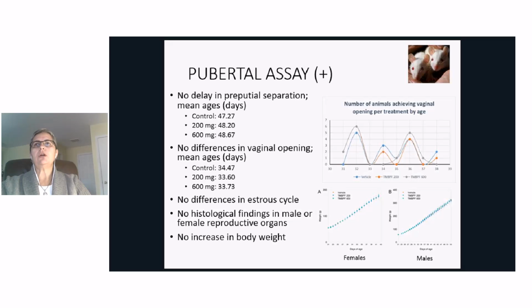And what we see is that there were no changes in the age at which the animals reached puberty. The animals treated with TMBPF and the control animals not treated with TMBPF all reached puberty more or less at the same time. There were no statistically significant differences. We also didn't see differences in the estrous cycles of the females. There were no changes in the weight or the pathology of the reproductive organs, both in males and females.